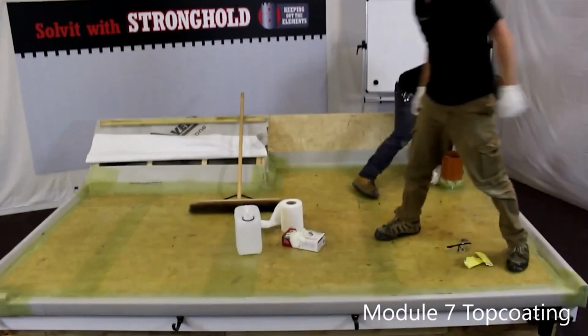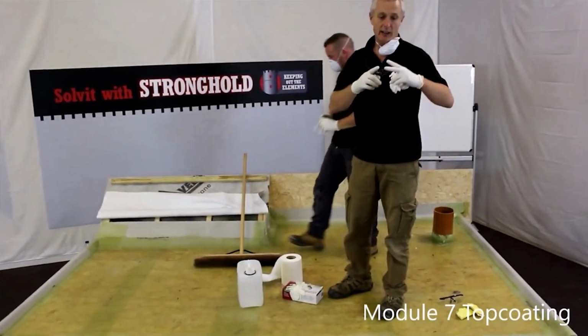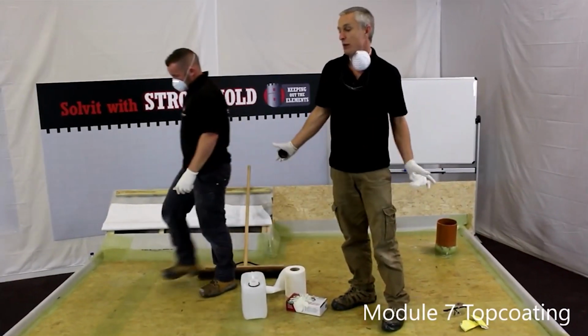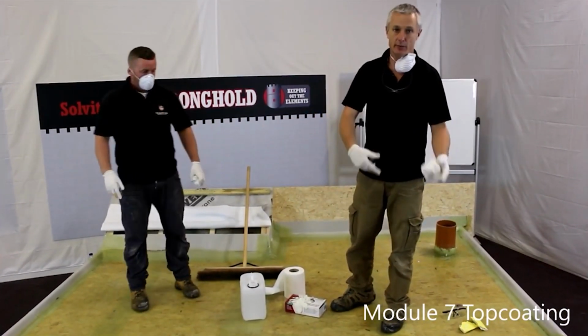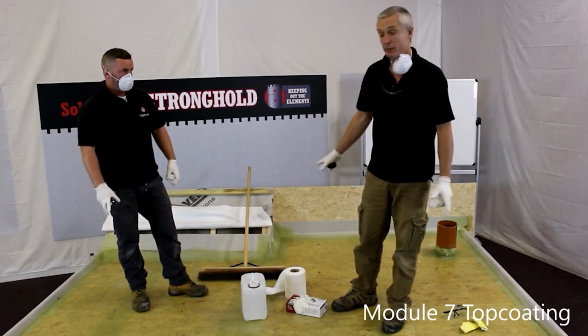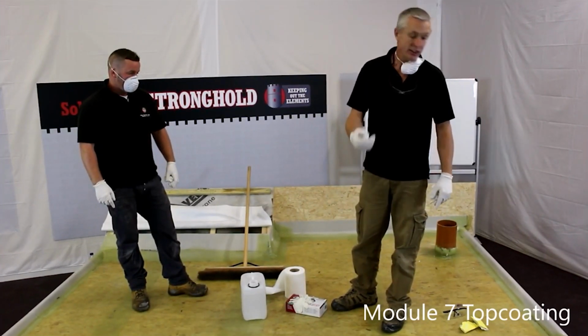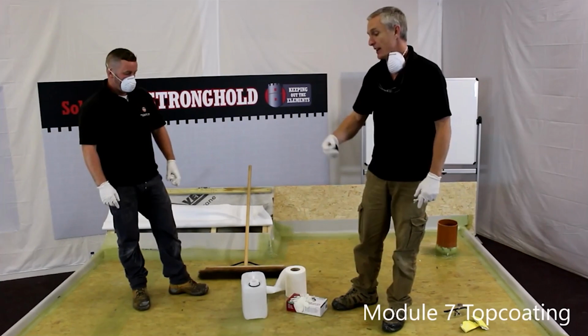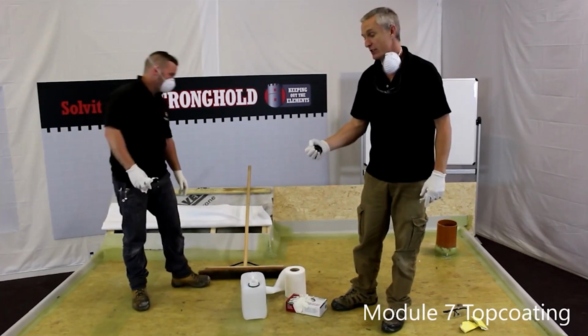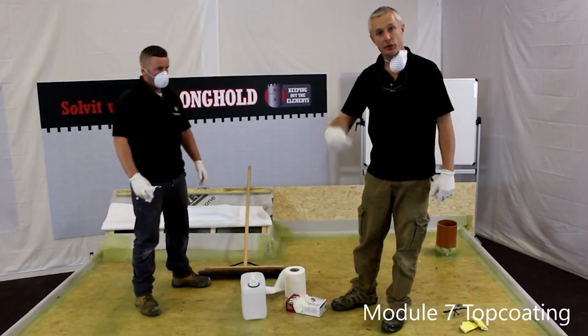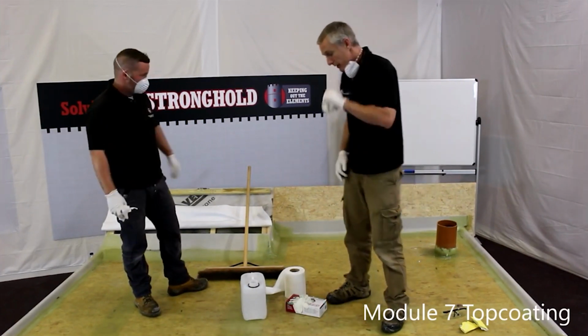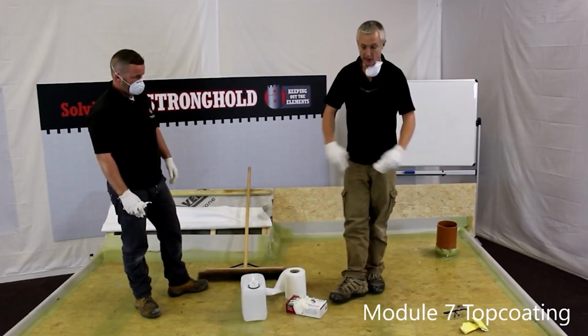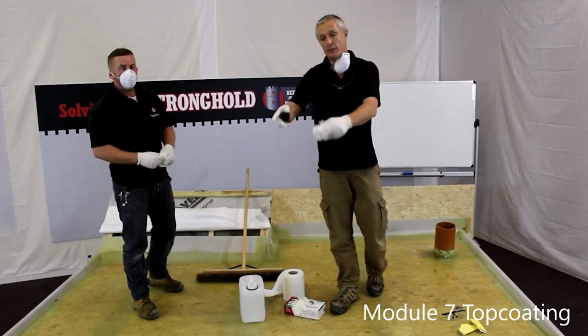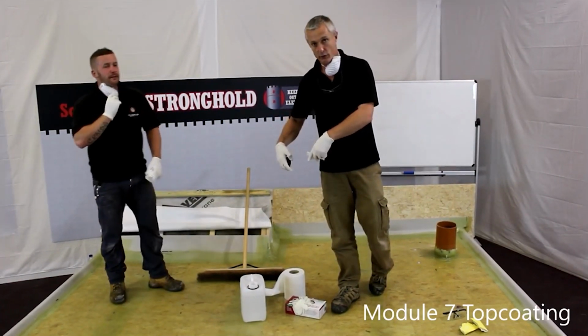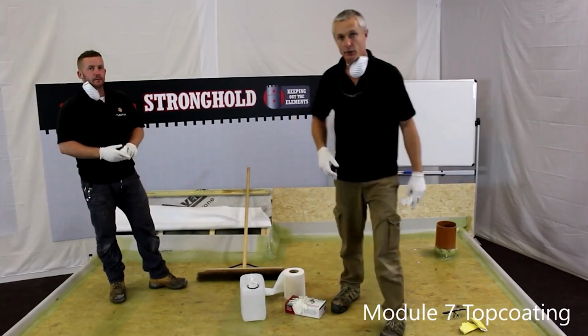Okay, so we've sanded the area to remove any glass strands sticking up. We've swept off the debris that we've generated by sanding it, and then we've wiped the area with acetone to degrease it, clean it, and, most importantly, to increase the strength of the bond when we put the top coat on the roof. So the next process, we're going to remove these materials from the roof and get the materials required for top coating onto the roof, and start again, so we'll see you shortly.